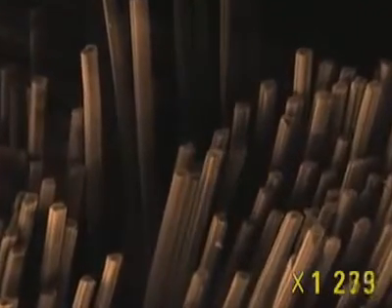Long grooves, some of them fairly deep, scar the surface of the fibers. When the material is bathed in resin, these grooves act as anchor points for the resin, ensuring maximum cohesion. On the side of the fibers, a few fragments — the result of natural breaks in the strands — stay attached.